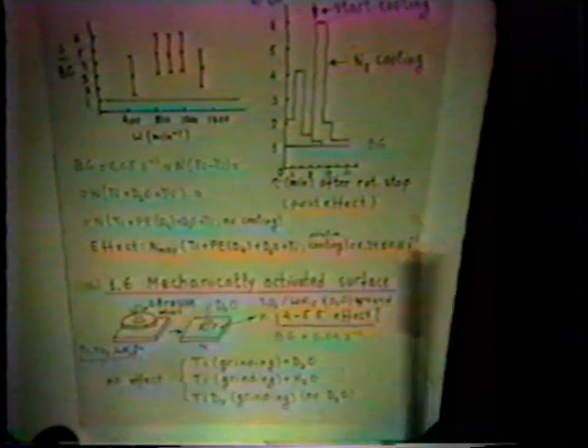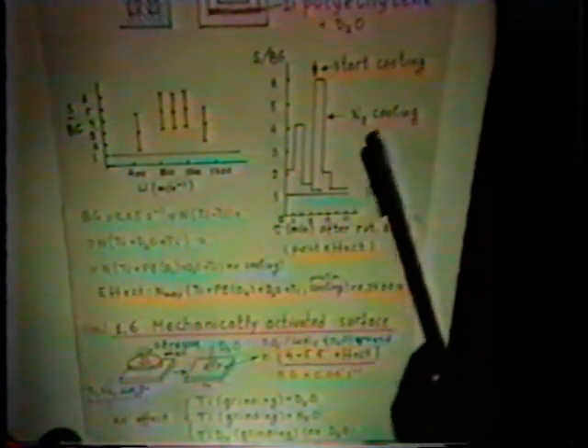However, for the following combination, when they used titanium pieces of the apparatus preliminarily cooled with nitrogen, they observed an effect which was about 5 times the background level. They also observed a post effect for about 10 minutes, and this post effect was especially large when they used additional cooling with liquid nitrogen.